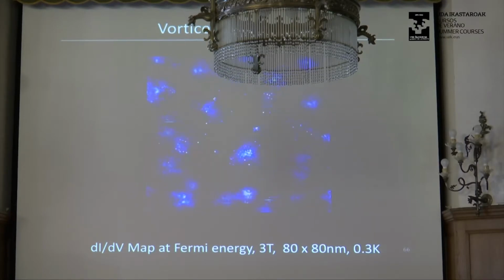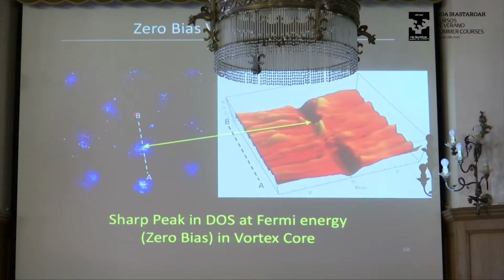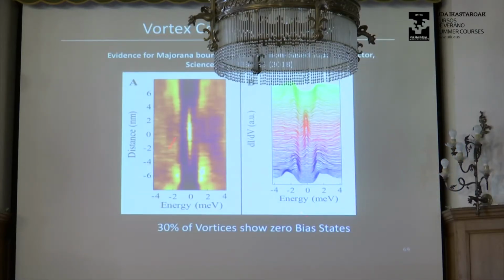So this is what, actually let me show you this one. This is what a dI/dV map looks like at 0 energy, right, where you should see these Majorana bound states. Each of these bright dots is the vortex core, right? This was done at 3 Tesla. And if you take a line cut across one of them, what you see is a sharp peak at 0. I'm not going to dwell on this mainly because this work was done by Hong Ding already, right? The thing I showed you was our data, but this is published data by Hong Ding and his collaborators. And you can see that they found vortices where they could see these sharp modes at 0 energy.